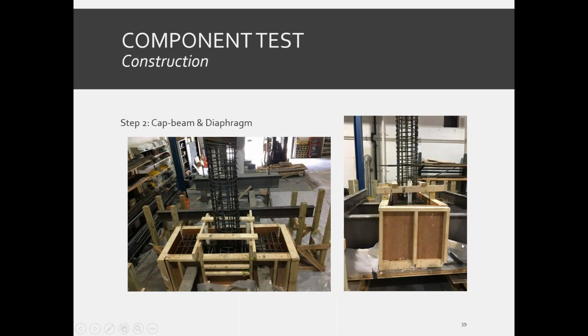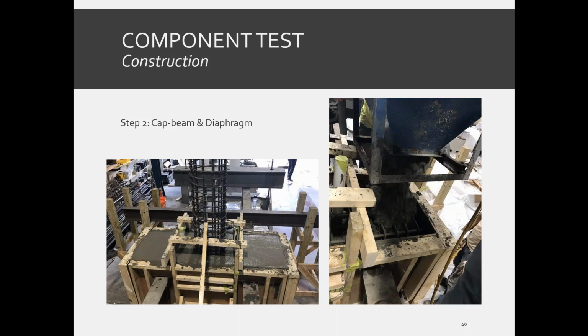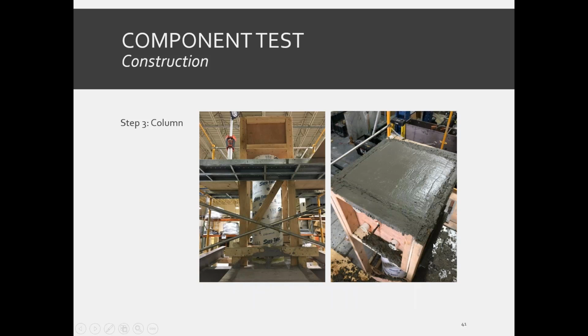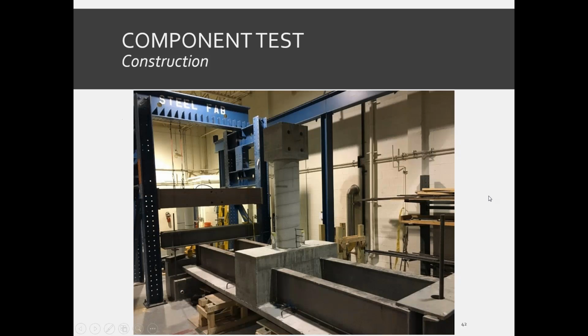This photo shows the casting procedure of the cap beam. The cap beam was casted 3 weeks after the first step. We have some additional photos for casting of the cap beam, and at the end, the column was casted. So this is the overview of the completed specimen. The auxiliary beams were removed and the supports under the deck were also removed. All components of the specimen were cured and covered with plastic sheets to prevent moisture loss.